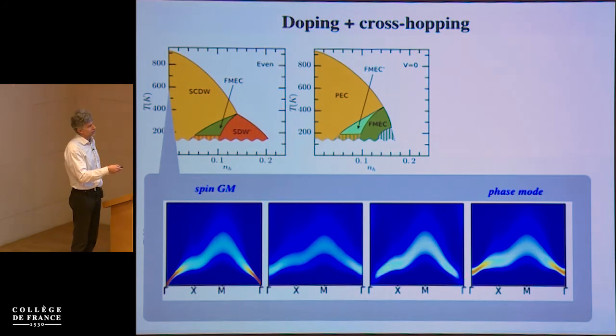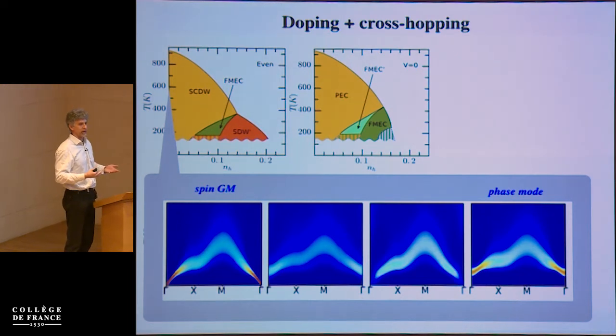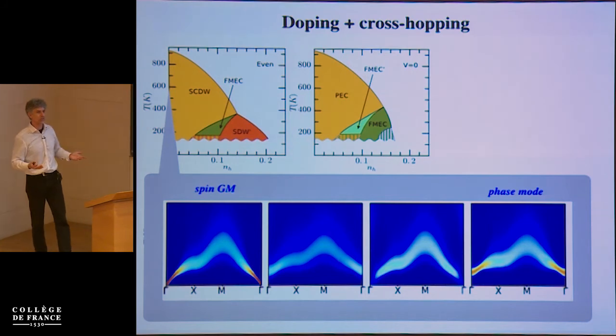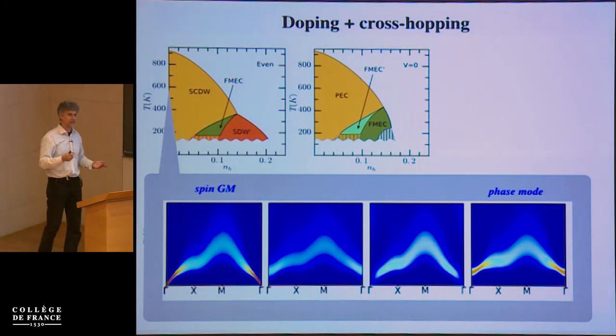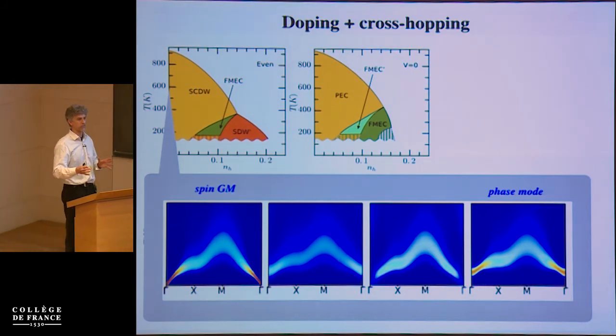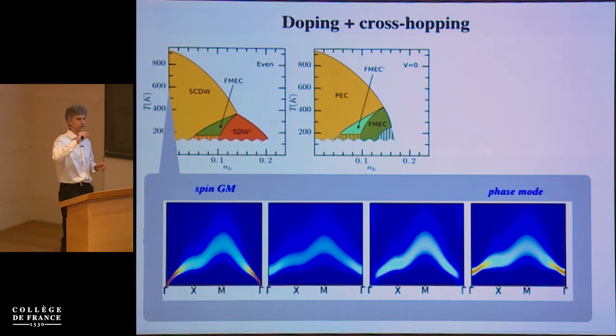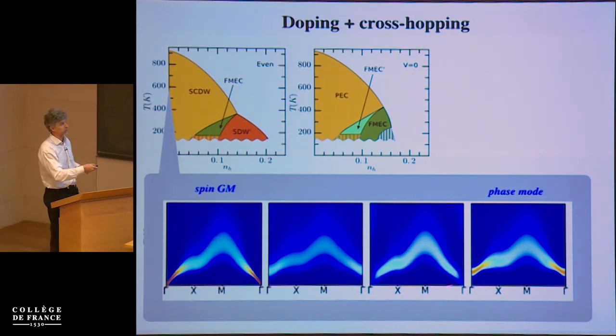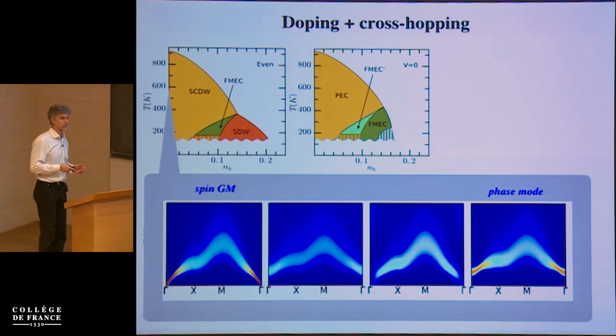So depending on whether its spectral weight remains in the same sector, it still corresponds to rotation of a phase, but it's now gapped. This is a very common situation in magnetic materials, right? You have a spin wave, but because of some magnetocrystalline anisotropy, you open a small spin gap. So this would be an analogical situation.